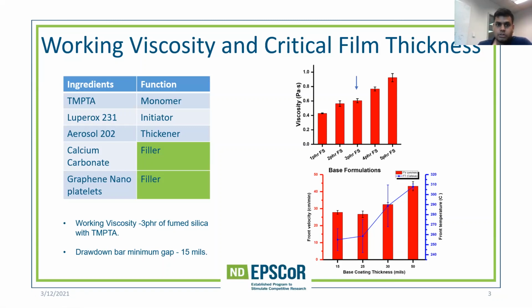To control the viscosity, we used Aerosil 202, it's fumed silica. And then, for further investigation or detailed discussions about how the front velocity and front temperature is impacted, we used calcium carbonate and graphene nanoplatelets as fillers. So as we can see in the graph that viscosity plays an important role, and with hit and trial, we found that 3 PHR fumed silica was required in the formulation mix to achieve a workable viscosity.